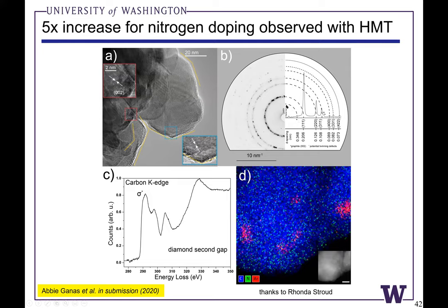We also see graphitic domains in the recovered material. Abby's also collected some electron diffraction images where we can see some hint of some lingering graphitic phase in this material. But also intriguingly, we might have some preliminary evidence of twinning planes from these recovered materials. But you can see in terms of the carbon K edge X-ray absorption feature, there's very little graphitic material in the sample. Abby has also observed nitrogen atoms doping these diamonds.